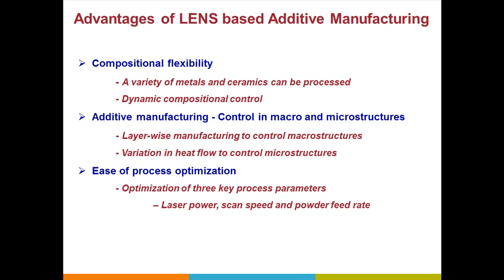The third thing, which is really big for us since we're at a university and deal with students, is that we don't need to do a lot of optimization of a variety of parameters. Really there are 3 parameters we play with: laser power, scan speed, and powder feed rate. So for us, if we're working with a new material, we like to see what's the minimum laser power needed that can melt it, and then the scan speed, how fast we move the stage, so the total energy input at the focal point of the laser is controlled by that. And then finally the powder feed rate.